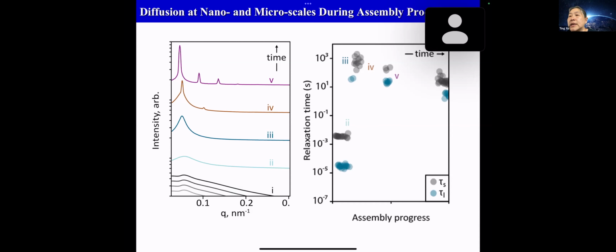What is interesting is that after the nanostructure forms, we see this direct correlation, a direct ratio between the tau S and tau L. It's about 10. And that's exactly corresponding to the Q they are looking at. It's basically saying that once the structure forms, the micro and the nanoscopic diffusion are completely coupled.